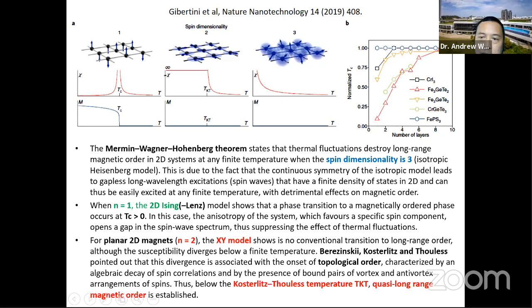Berezinskii, Kosterlitz, and Thouless have pointed out it's got to do with topological order. In fact, these systems below a certain temperature, known as the Kosterlitz-Thouless temperature, T_KT, have quasi-long-range order, which is a sort of magnetic order. So in 2D magnets, we can expect to see these topological effects that give some kind of long-range order. And in the data you see at the top right of different materials, you can see the Tc decreasing as the number of layers decreases.